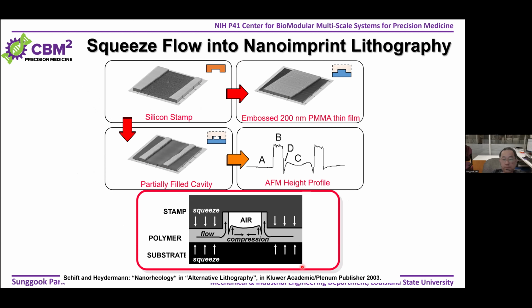Now, once you apply pressure at a temperature above the Tg, what happens? This is the case in nanoimprint lithography. Once you apply pressure to a thin layer of thermoplastic polymer, you have a squeeze flow. Squeeze flow means that upon pressure, the polymer, mostly at the top of this film, flows laterally to fill into the cavities of your mold structures.